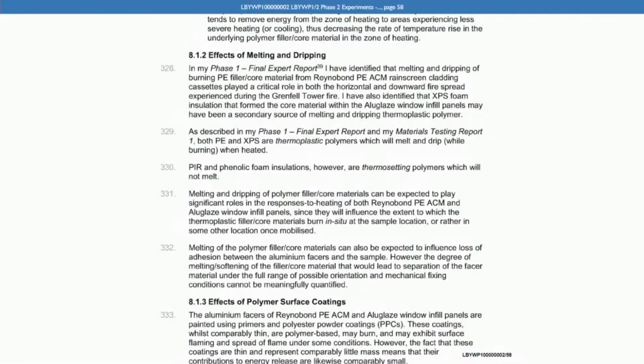Yes, I see. Now, if we go then to page 58 of your report, please, let's look together at paragraphs 328 and then 330 on that page, under the heading Effects of Melting and Dripping. And at 328, you say this: in my Phase 1 final expert report, I've identified that melting and dripping of burning PE filler/core material from Reynobond PE ACM rain screen cladding cassettes played a critical role in both the horizontal and downward fire spread experienced during the Grenfell Tower fire. I've also identified that XPS foam insulation that formed the core material within the Aluglaze window infill panels may have been a secondary source of melting and dripping thermoplastic polymer. And then at 330, you say, PIR and phenolic foam insulations, however, are thermosetting polymers which will not melt.